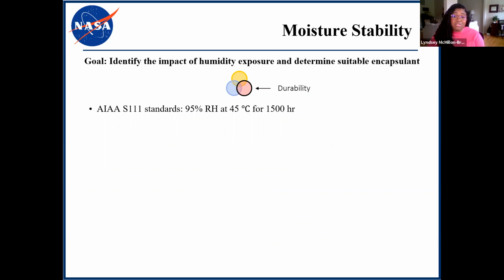So I want to shift gears a bit and share some recent results from our lab on how these materials endure exposure to moisture, because I mentioned earlier that's another challenge point. And we're still focusing on durability here. So when exposed to humidity, the perovskites' hygroscopic amine salts decompose, and that results in device degradation, fairly significantly so.